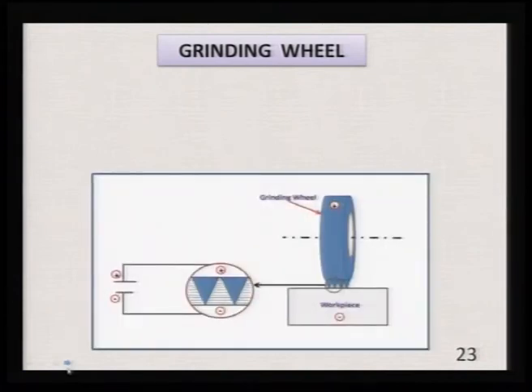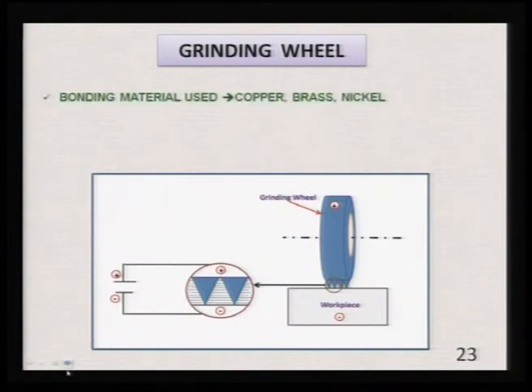Now, here you can see the bonding material, which is used for bonding the abrasive particles in the electrochemical grinding wheel as shown over here, and the bonding materials are copper, brass, nickel, because they should be electrically conductive. So, these materials have good electrical conductivity, so they are commonly used as bonding material for electrochemical grinding wheels.